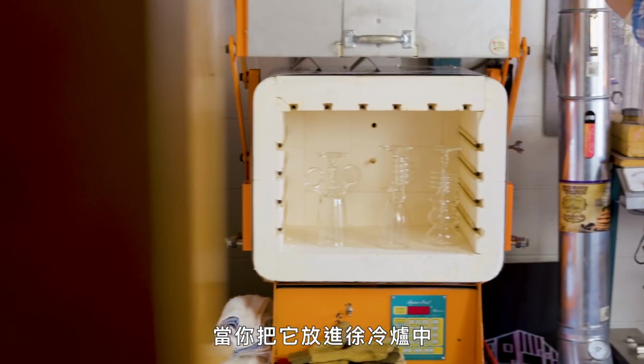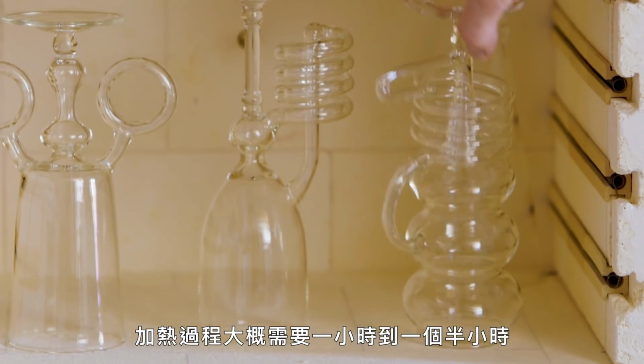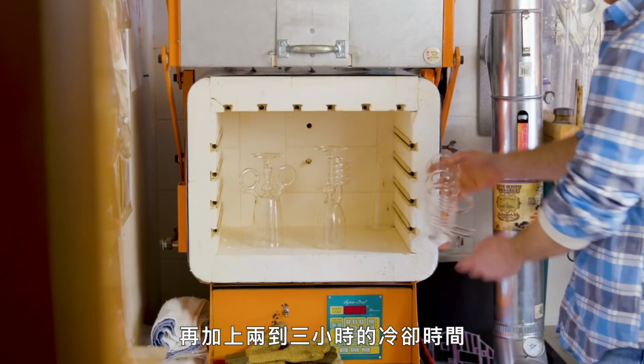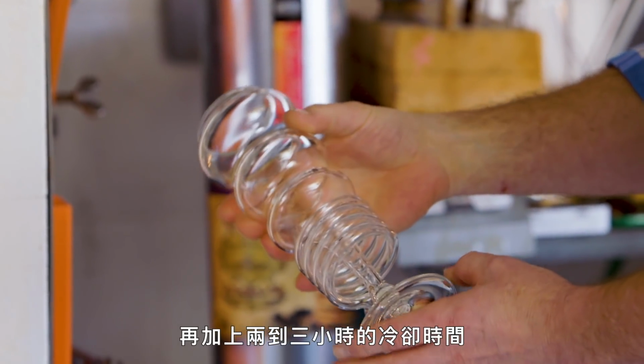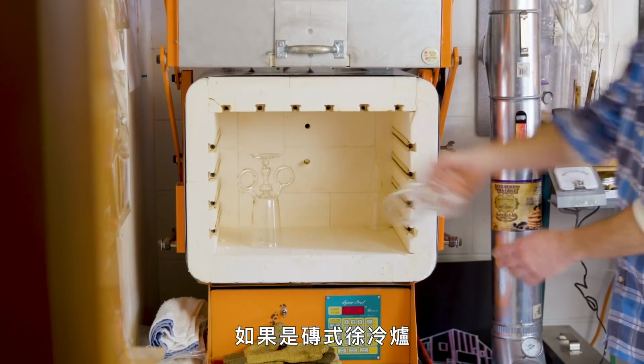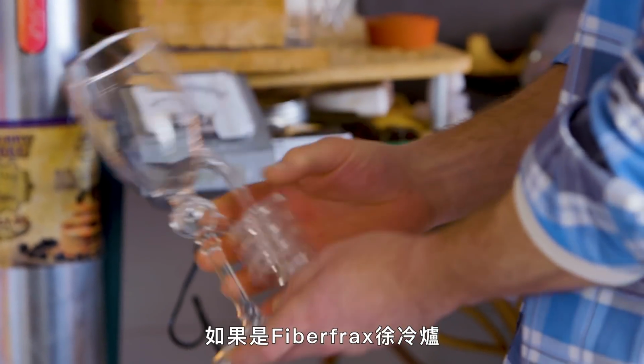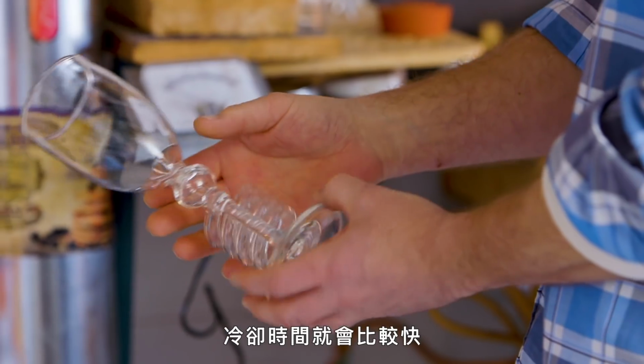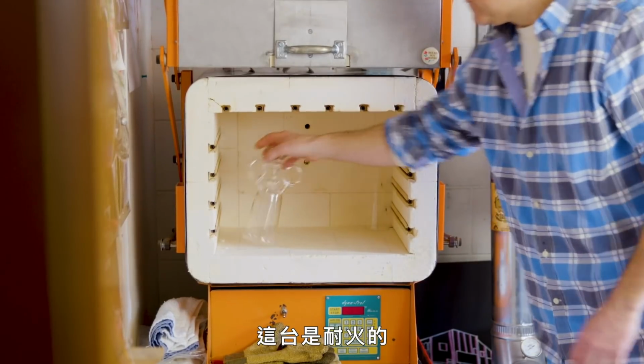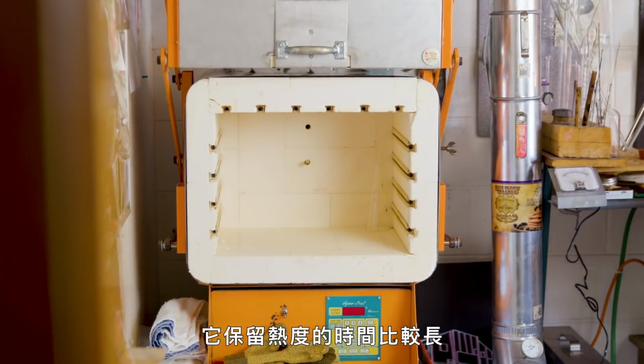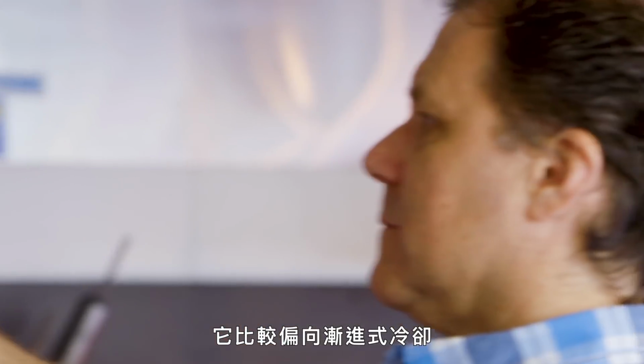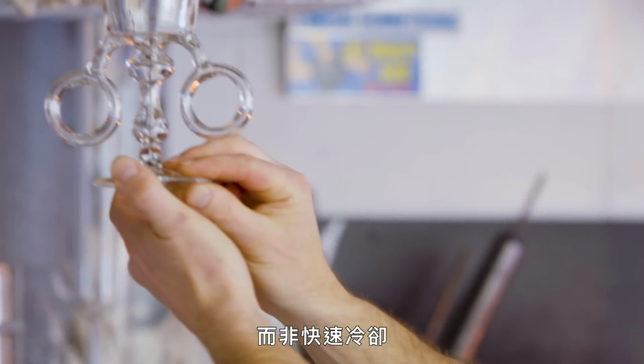My annealing oven, that process usually takes about an hour, hour and a half to get up to temperature, and then about another 2 or 3 hours to cool down, depending on your oven. If you have a brick oven, it will hold the heat longer. If you have a Fiberfrax oven, it will cool a lot faster. I have one that's fire brick, so it holds the heat longer, and it's more of a ramp down cooling versus a shelf drop off cooling.